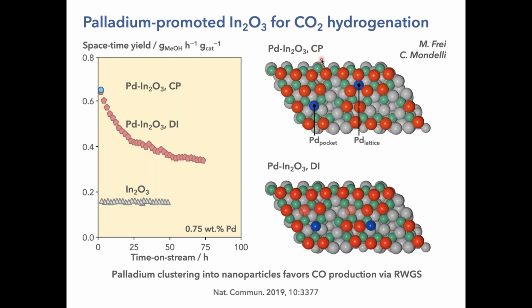That's co-precipitation. By co-precipitation, playing deeply with the recipe, which is not an afternoon job, by the way, you could tailor the fraction of palladium that is in the lattice of the indium oxide with respect to the fraction of palladium that is on the surface of indium oxide. This can be tuned because some of the palladium is going to be basically substituting indium in the co-precipitation process. But upon saturation of the lattice by palladium, the remaining palladium will be actually on the surface of the catalyst, right? And we know this is buried on the subsurface, so it's not going to be active.